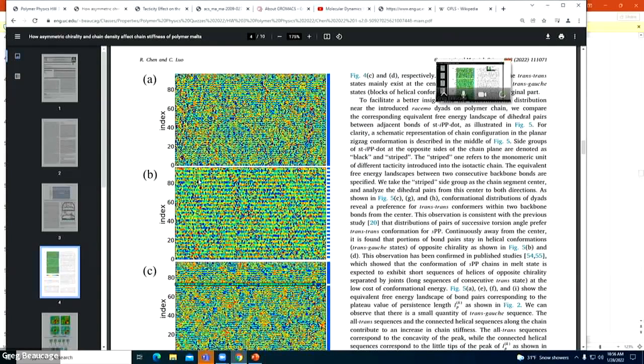When you make it syndiotactic, there's a lot less blinking of the lights. So things are happening much slower. So the syndiotactic holds its structure better. I don't think that was known before this paper. If it's true, I mean, it's a simulation. You could say it might not be true, but it's kind of odd that the dynamics of the syndiotactic is much slower than the dynamics of the isotactic.